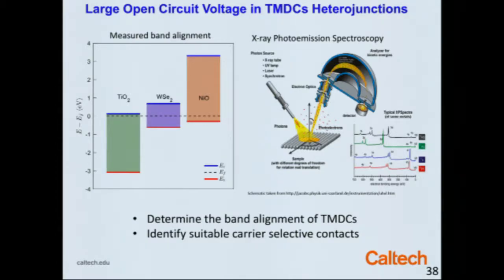So the other thing we want to do is create the proper conditions for achieving high voltage. Previous to our work, the voltage records were about 200 millivolts for these chalcogenide materials. But of course, everything we know suggests that what we want is carefully band-aligned materials — we want selective contacts to selectively extract the holes or the electrons.